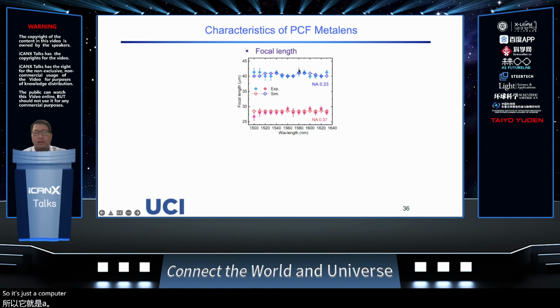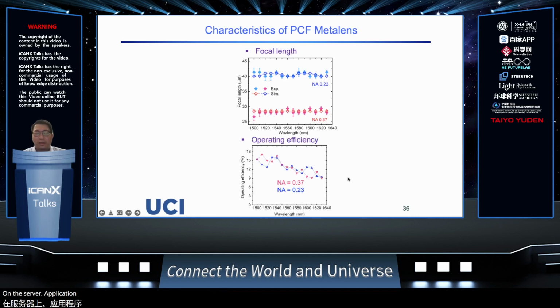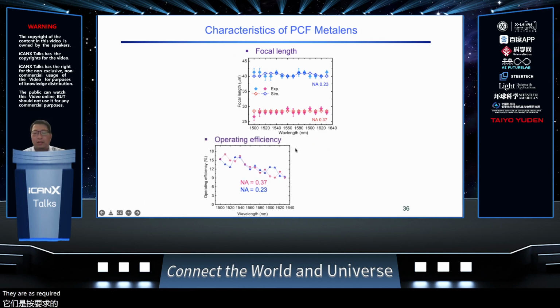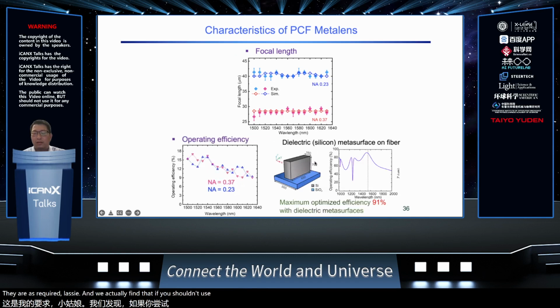Just to give you a little bit of numbers here, this is the focal length. You can see across this telecommunication wavelength, we have a really constant focal length on this fabricated structure. And the efficiency here is around 15% in the telecommunication wavelength, which is also quite decent. But certainly this could be further improved because we're using metallic structure. They are actually quite lossy. And we actually find that if we use a dielectric, let's say a silicon metasurface, we can enhance the efficiency to 91%. Which means really high efficiency lenses on fiber.